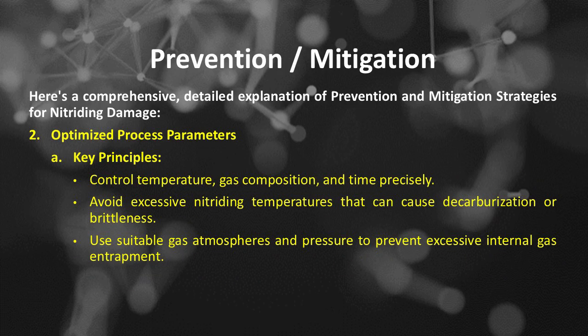Number 2 of prevention and mitigation strategies for nitriding damage is optimized process parameters. The key principles include: control temperature, gas composition, and time precisely, avoid excessive nitriding temperatures that can cause decarburization or brittleness, and use suitable gas atmospheres and pressure to prevent excessive internal gas entrapment.